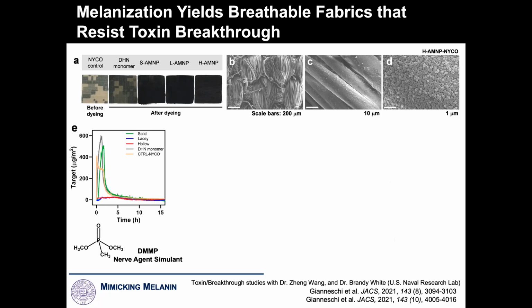last year. And so what did we get? So this is the data here. This is a nerve agent simulant that's actually an insecticide, but it's very similar in structure to nerve gas agents. What you're seeing here, you can squint at this, but what basically is going on here is that you impinge the gas on the fabric itself, and then you look for how much leaks through in time.